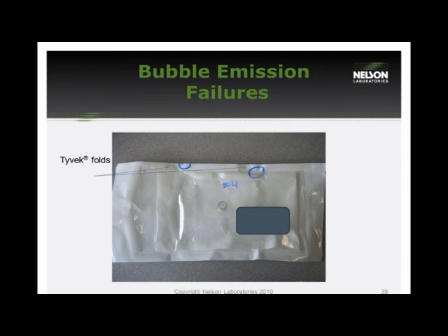This is a picture of a common failure that we see with this test. A lot of times people will just buy pouches that are available over the counter and put their device into it. Then they'll fold the package and place it inside a box. As you can see, when you fold Tyvek, it has the opportunity for the seal to separate from the Tyvek material, which will then produce failures. So it's very important to put the work in up front to make sure that your device fits into the package appropriately rather than trying to fit the package to the device.